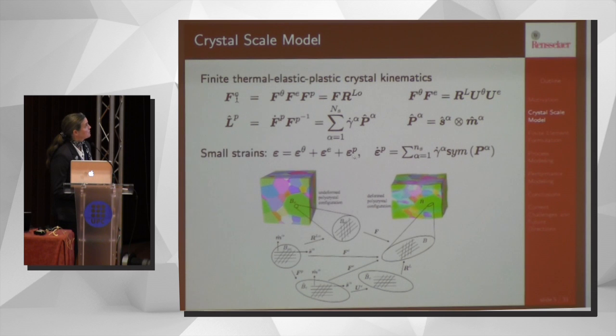The plastic part, which is probably the most interesting part, we assume is associated with slip along crystallographic slip systems. So the plastic velocity gradient is a sum over all the slip systems of the rate of shearing on each slip system, gamma dot alpha, times the Schmid tensor, P hat alpha. Hat indicates the lattice configuration. That Schmid tensor is the dyadic product of the slip direction and the slip plane normal.